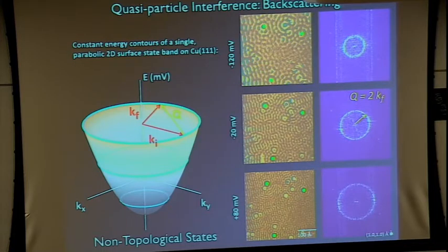That's a good question. The susceptibility is the largest there, and that's basically what you're imaging in this experiment. So you should see some signal in here, and there is a signal there, but it is very weak compared to the very large susceptibility you get when you're looking right at the Fermi edge, if you like. You're going to see a lot of examples of this as we go along. So this is just 2kF. You can go to ARPES and measure this at this energy and just read it off of this map. This is a Fourier transform of these pictures. So this is quasiparticle interference.